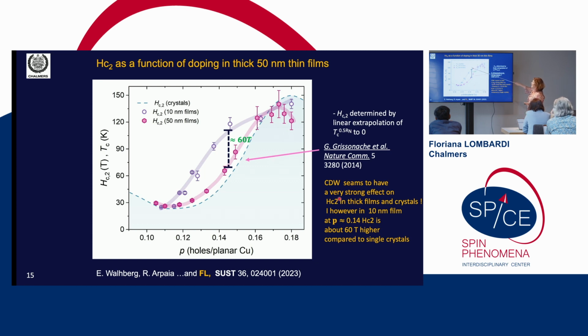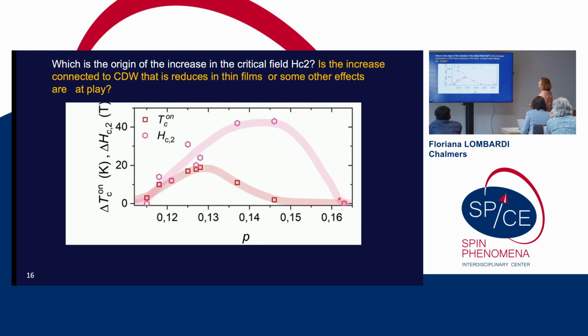But for 10 nanometers at the same doping, you have the extrapolated HC2, which are 60 Tesla higher. So what is the origin of this increase? Is it the charge density wave? Because in our thin films, the charge density wave volume is effectively reduced because it has become one-dimensional, or it is something else.